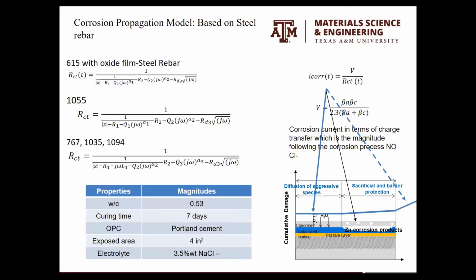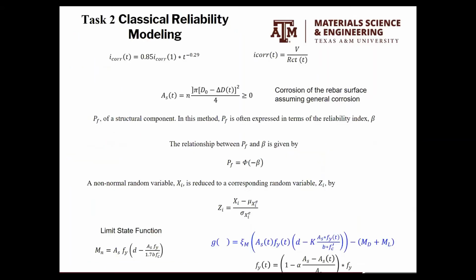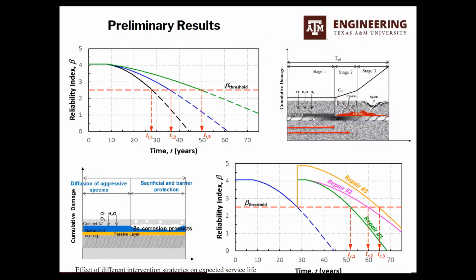At the end of the presentation I'm going to mention this, but that's the classical reliability model you see on the left. This is pretty much what we built with the corrosion rate based on the characteristics of the concrete. On the right, you can see the characteristics not only of the concrete, but also the rebar. And at the end, both corrosion rates can now follow the classical reliability model that is based on the change of the area of the rebar, and that puts a capacity, and that puts a reliability in terms of a limit state function which is defined here as G, and is based on the area that is decreasing. This is based on the general corrosion rate, and the capacity based on the loading. And we have this outcome based on the classical reliability modeling.